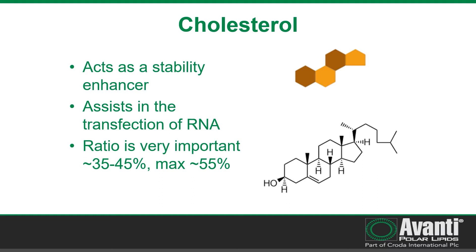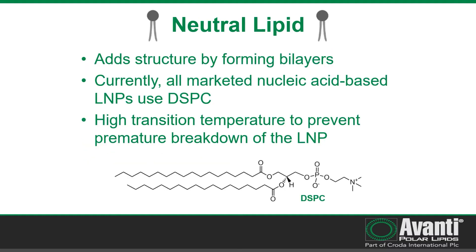Along with cholesterol, the neutral lipid adds structure to the particle as it helps form the bilayers. The neutral lipid is a phospholipid, and currently all marketed nucleic acid-based LNPs contain the same neutral lipid: DSPC. DSPC is often used in other lipid particle systems as well. It is composed of a phosphocholine head group and two saturated 18-carbon fatty acyl chains. DSPC has a transition temperature of about 55 degrees Celsius. This relatively high transition temperature helps prevent premature breakdown of the particle once circulating in the body.